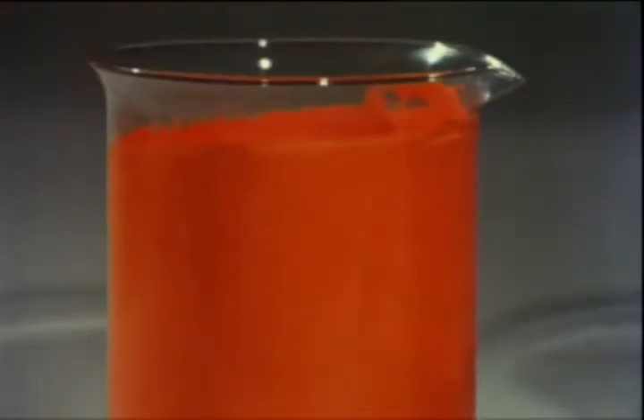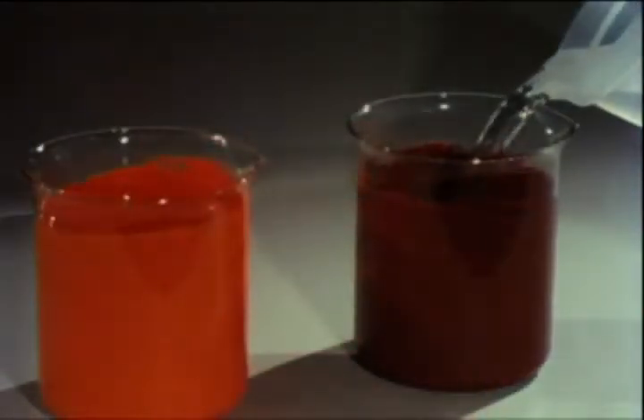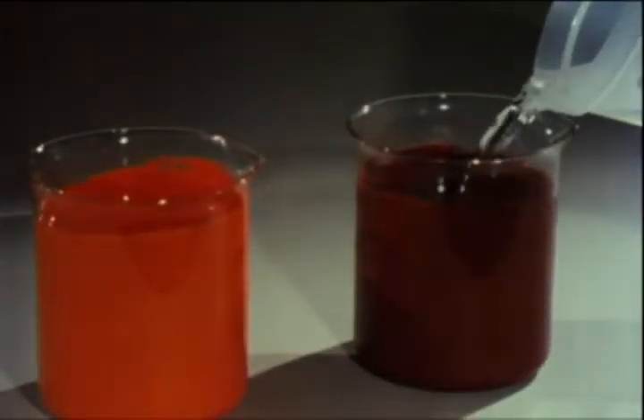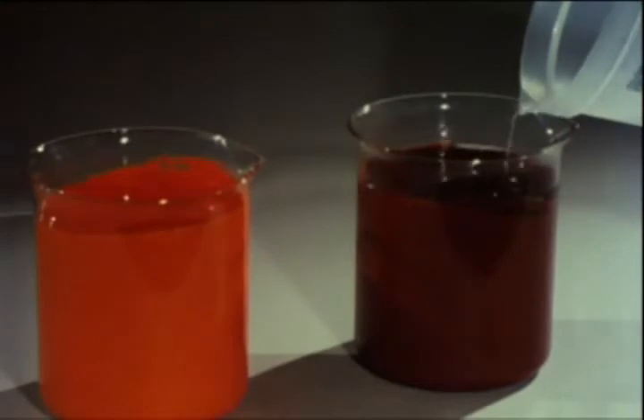Chromates in paint act in this way, and so does the compound formed from red lead in linseed oil. The inside of one beaker was coated with linseed oil and red lead, and another with linseed oil and iron oxide. After drying for a few days, each is filled with distilled water, which penetrates the linseed oil film.